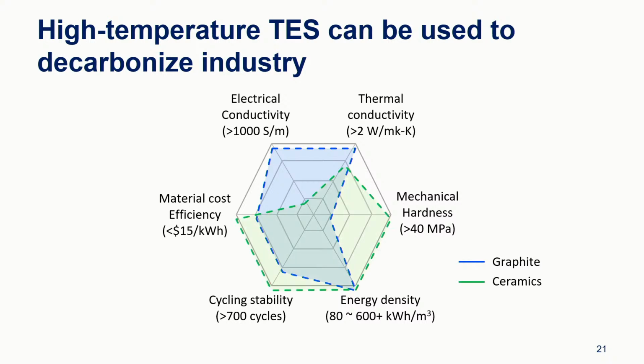And then if we look at ceramics, it does pretty well for most properties, except it's not electrically conducting, and its thermal conductivity is also a little bit lower. And we want a high electrical conductivity to charge the material with electricity, just by joule heating. And we want a decently high thermal conductivity so that you can extract the heat easily.